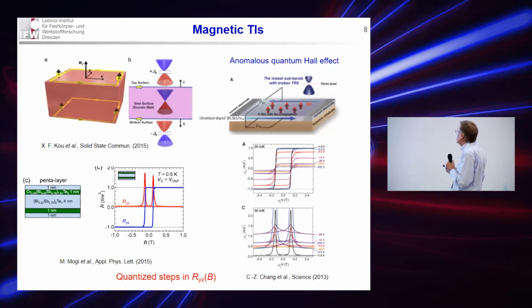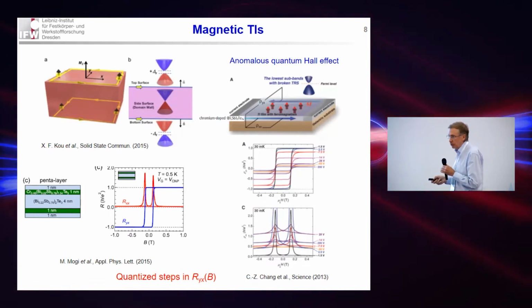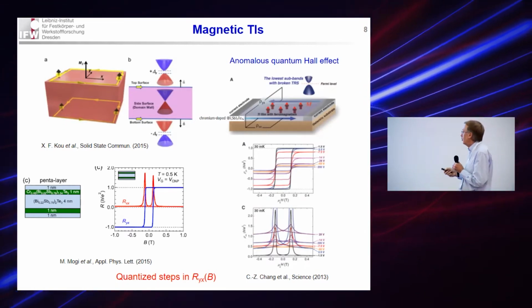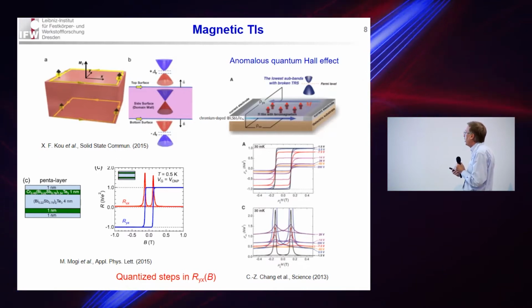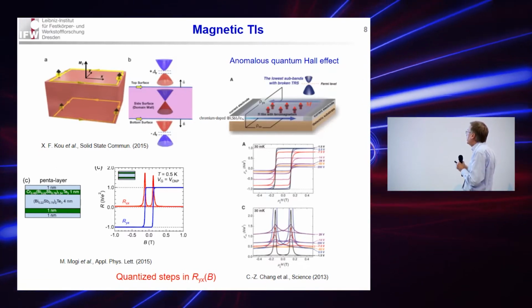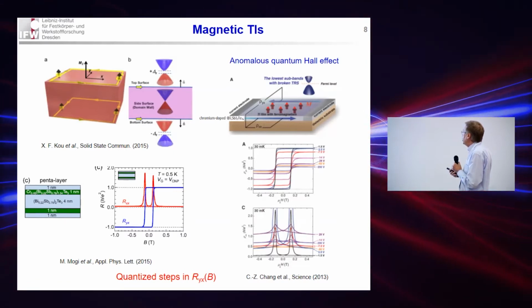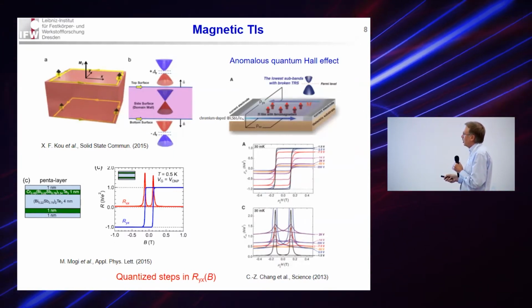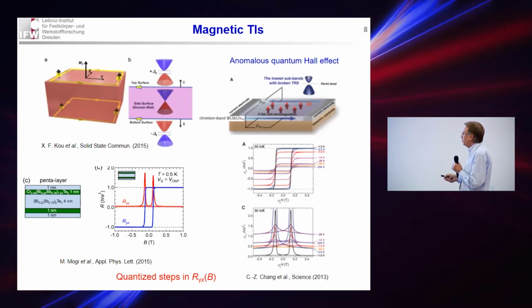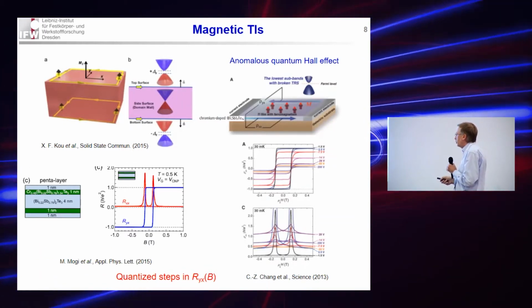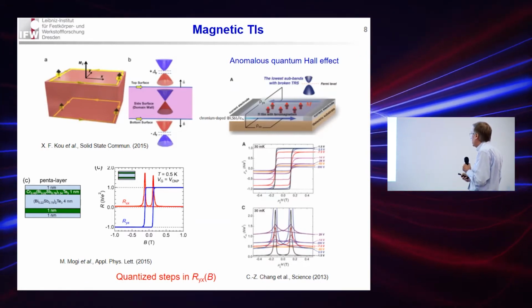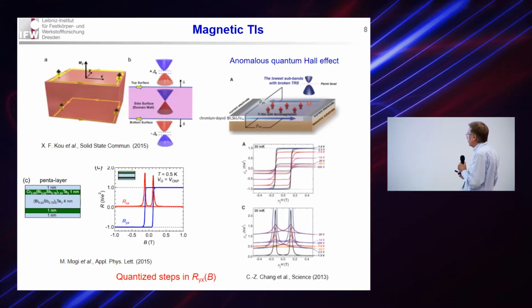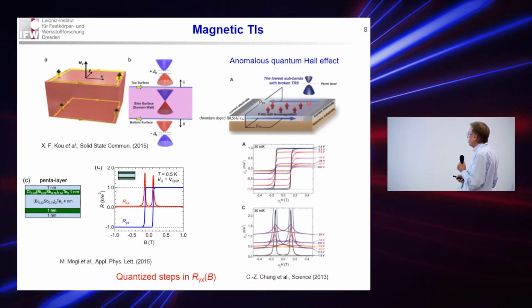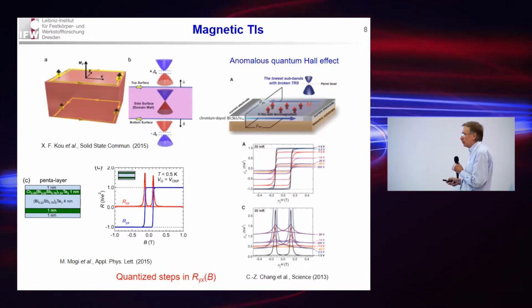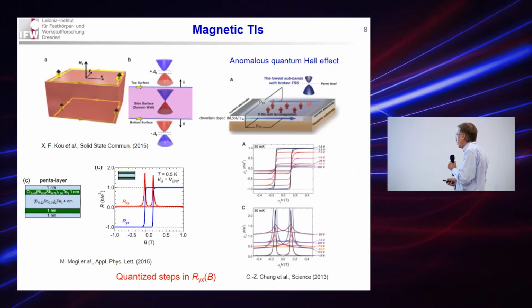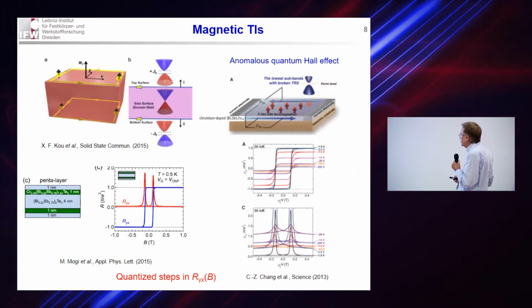One would be just simply to dope a non-magnetic topological insulator like bismuth selenide or bismuth telluride with something magnetic like chromium ions. The chromium spins order magnetically, and they generate the out-of-plane magnetization. Or one can make a heterostructure with a non-magnetic topological insulator topped with, say, a topological insulator doped with magnetic impurities. In both cases, it was really strictly experimentally confirmed that this is a magnetic topological insulator showing the quantum anomalous Hall effect, which is visible very clearly.